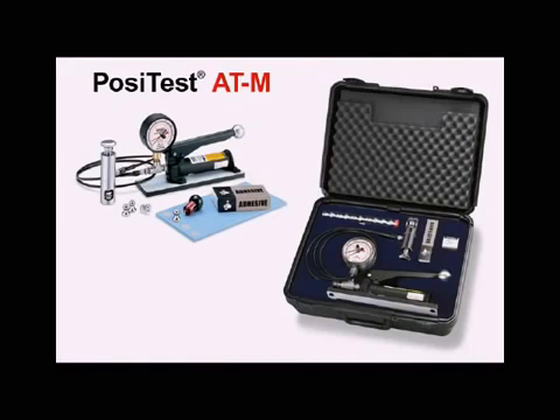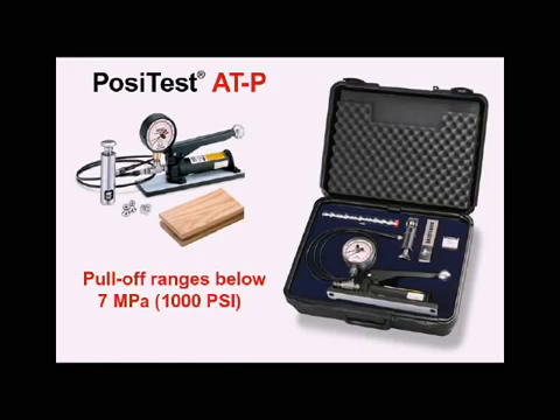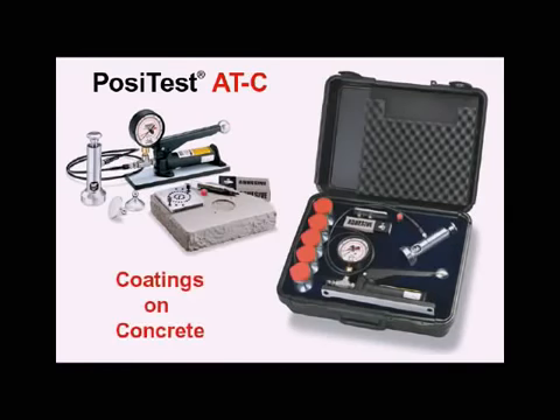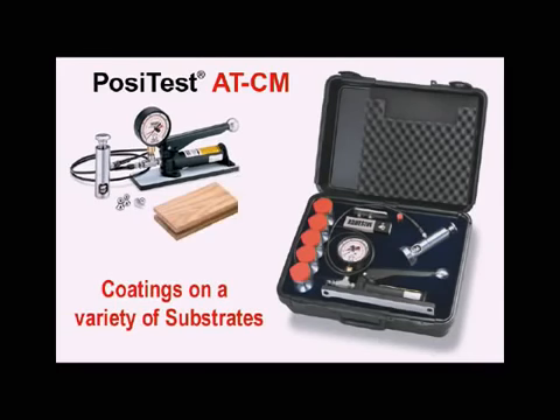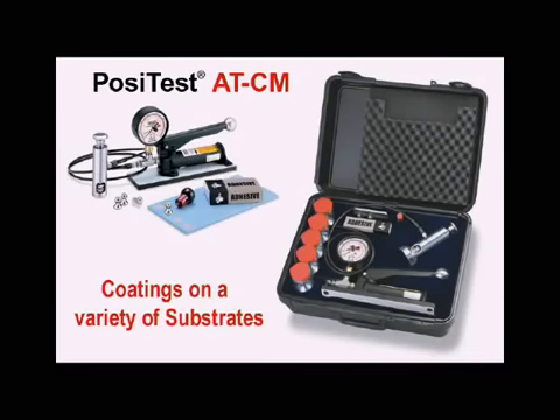A 20 mm dolly available with the M model is ideal for measuring on metal substrates. A higher resolution P model is available for expected pull-off ranges below 7 megapascals, 1,000 pounds per square inch. For masonry substrates such as concrete, the 50 mm dolly available with the C model is preferred. A more universal solution, the CM model, is available for customers with applications on a wide variety of substrates.